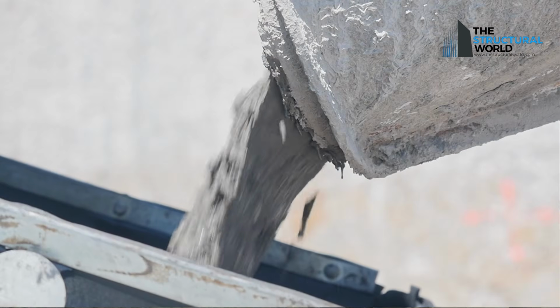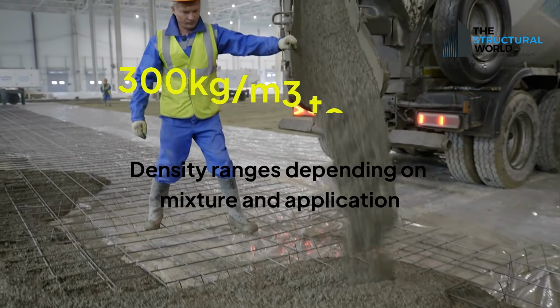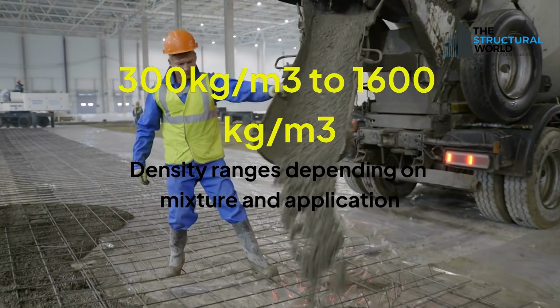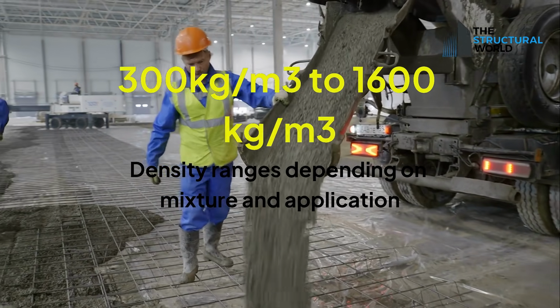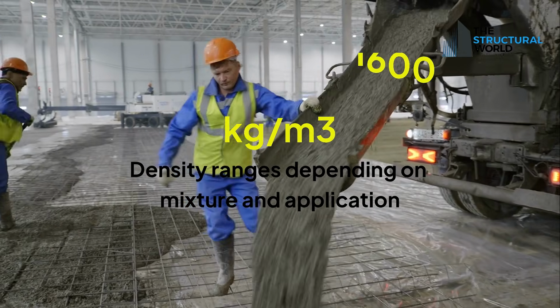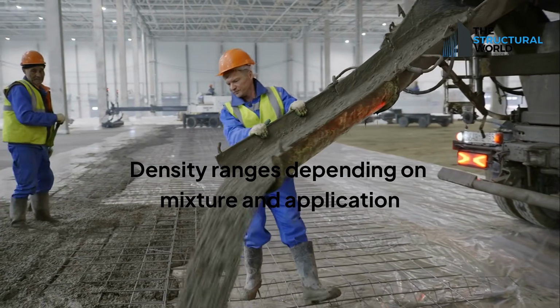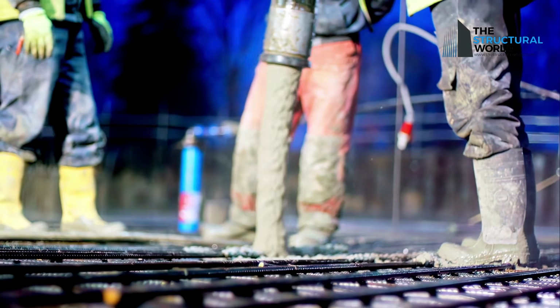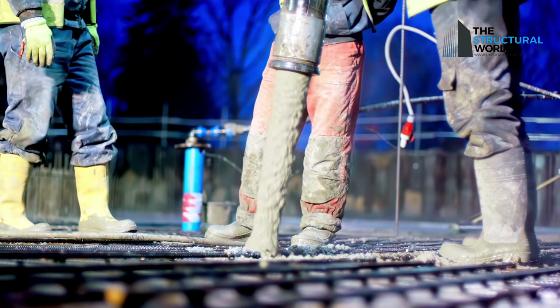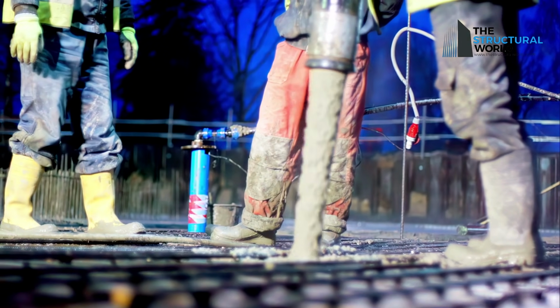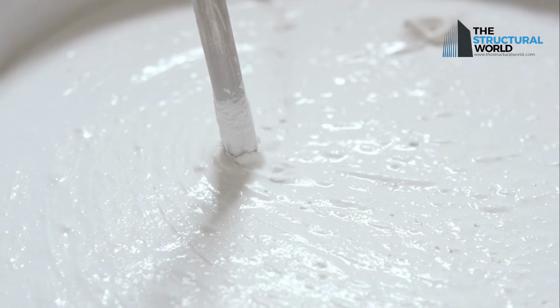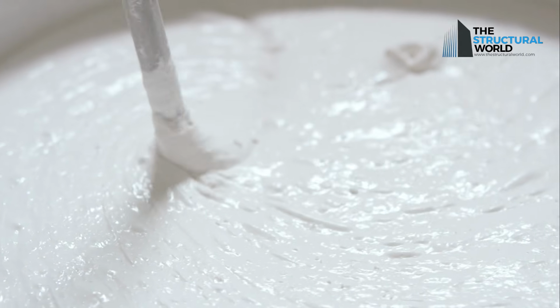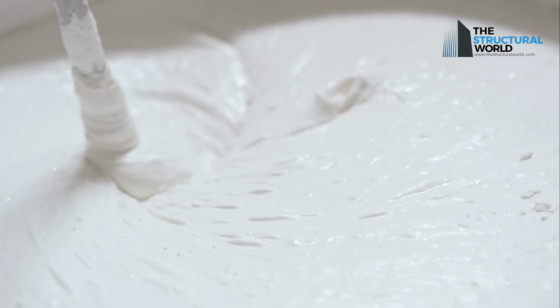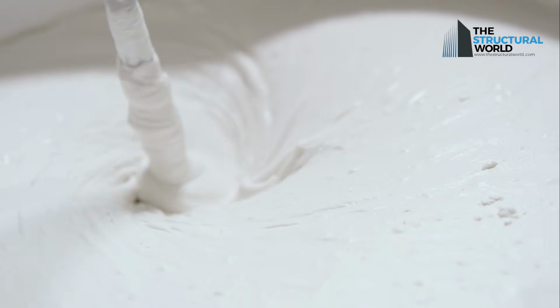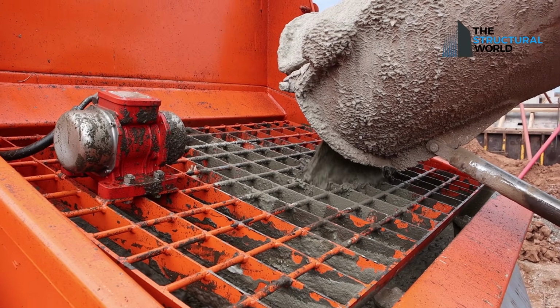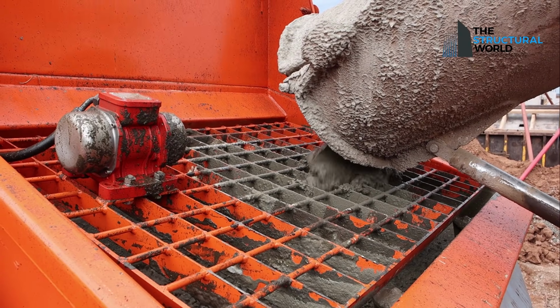Depending on the mixture and its applications, the density ranges from 300 kg to 1600 kg per cubic meter, compared to normal weight concrete, which is 2400 kg per cubic meter. The minimum compressive strength of foam concrete is 2 megapascal, or 20 kg per square centimeter. It can be achieved by mixing liquid cement grout or sand cement grout with a foam made by a foaming agent. The type of foaming agent varies in accordance with the supplier's properties and specifications.